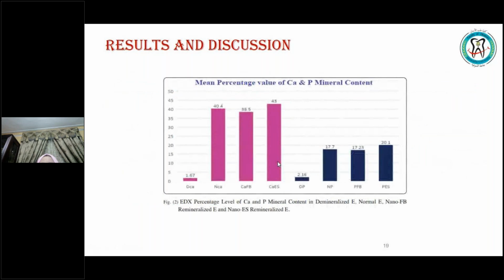Lastly, we collected all the data and put it in a histogram to compare all, where the D here represents the demineralized enamel surface, where the calcium was 1.67. The calcium in the normal enamel was about 40, as we have seen in the tables. For the fish bone remineralization, the calcium was 38.5, where the calcium for the eggshell was the highest of all, that was 43. Again, the phosphorus for the demineralized enamel is 2.16. For the normal, it is 17.7. For the remineralized enamel surface with fish bone, the phosphorus level was 17.23, and for the eggshell, the phosphorus was 20.